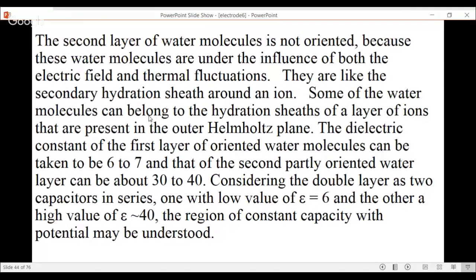Some of the water molecules can belong to the hydration sheaths of the layer of the ions that are present in the outer Helmholtz plane. We are assuming a constant dielectric constant throughout the solution, but it is not true. The dielectric constant of the first layer of the oriented water molecules can be between 6 and 7. Okay, let us assume less than 10. The second partly oriented water molecule layer can be 30 to 40. Okay. Whereas in pure water it will be much higher.